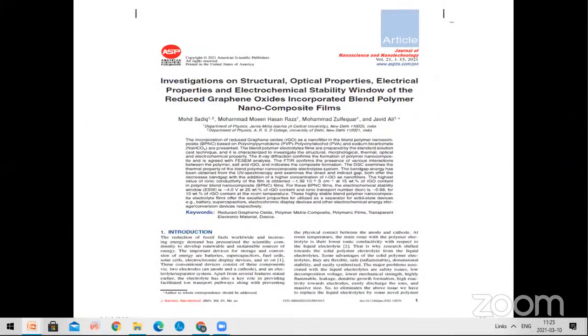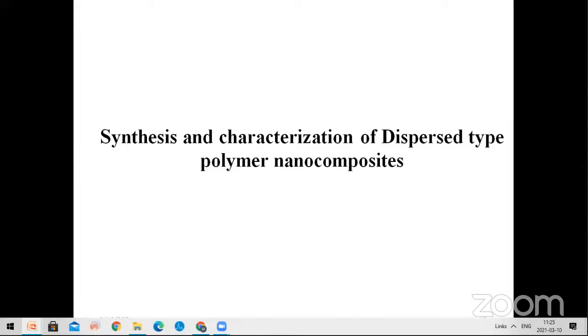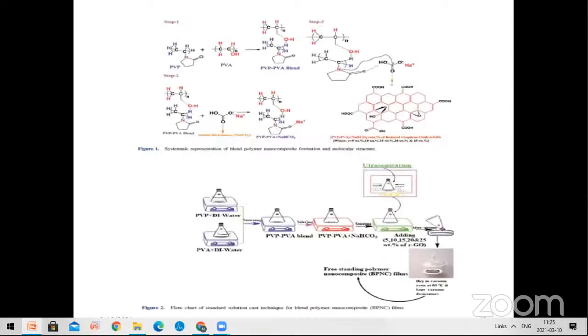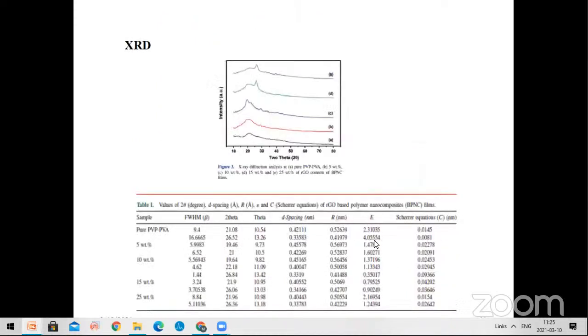Another one is the investigation of the structural, optical, and dielectric properties of the nanocomposite based electrolyte film. In this study, we synthesize and characterize the dispersed type nanocomposite film. Here we take PVA and PVP, and we take different weight portions of the RGO doping in the polymer salt complex. Then we take the